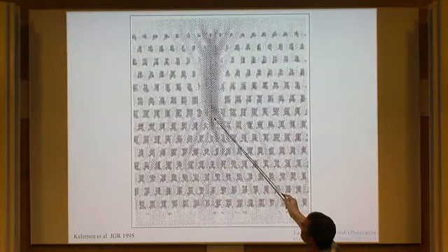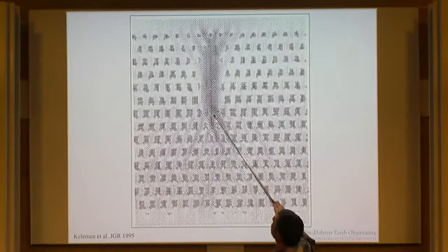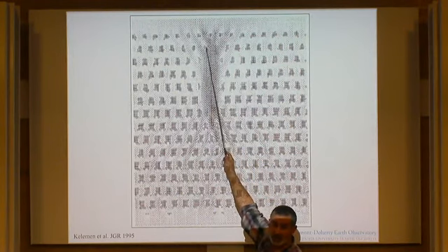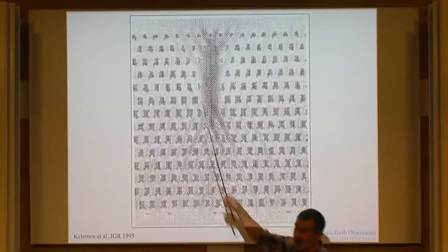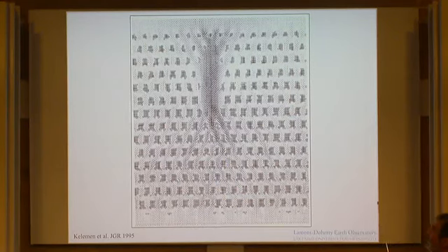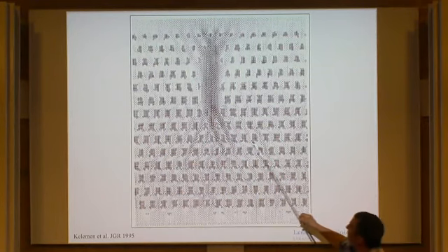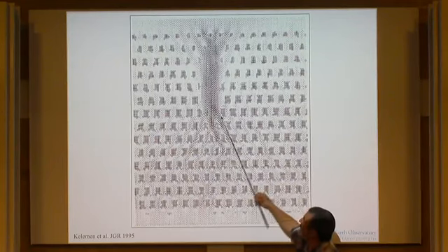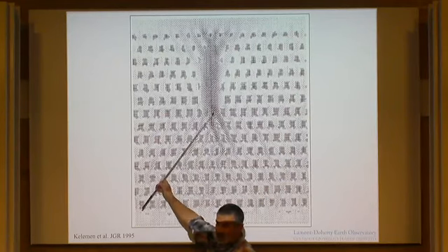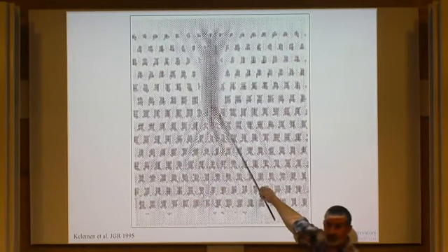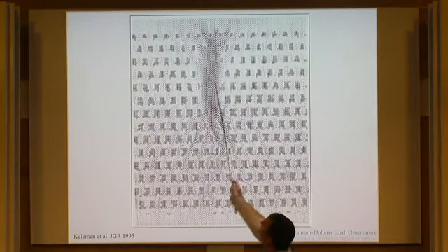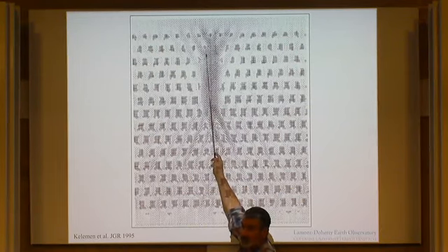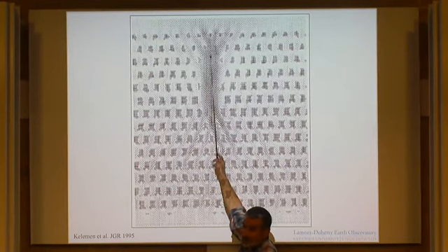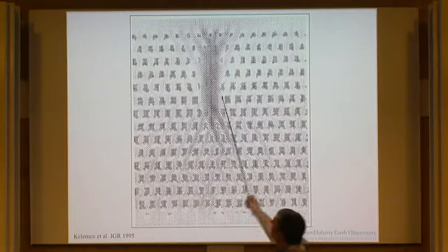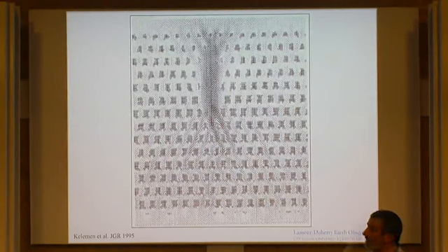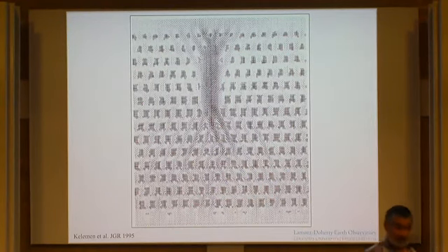And at this point in the model, there is actually a solubility front at this end where the fluid is very far from equilibrium with solid particles in the middle of the channel. Okay, so this is how these things might arise out of a continuum. There's also some nice things to see in here about how the fluid pathways develop. So you see this coalescence upstream from the channel, and you see divergence where the permeability at the head of the channel begins to go down. Okay, it's just Bernoulli, but it's a good idea to keep this in mind when we think about how the solid system evolves over time and what sort of coalescence networks might form and unform.